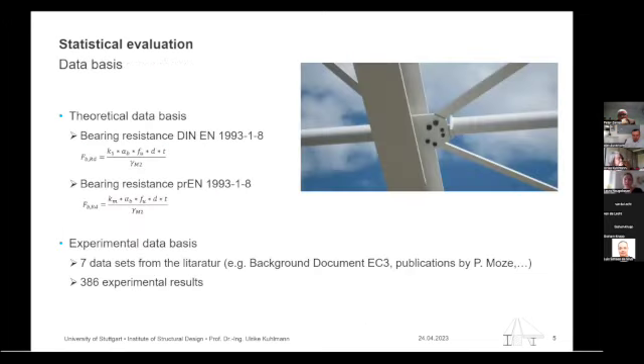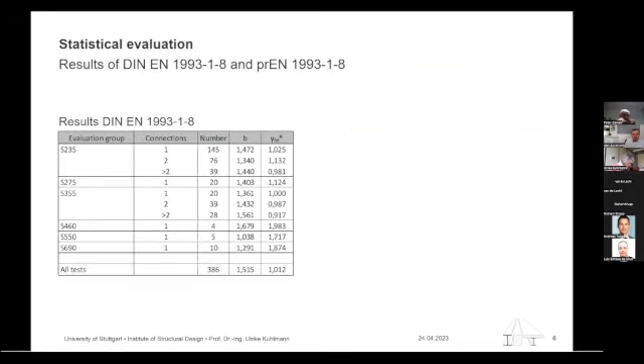The base for my statistical evaluation was the following. I had the theoretical database: the bearing resistance according to DIN 1993 and the bearing resistance according to the draft prEN 1993. As the experimental databases, I used 7 data sets from the literature, for example, the background document of the EC3 or a publication by P. Moze. All in all, I had 386 experimental results. I now want to continue with the results of the evaluation.